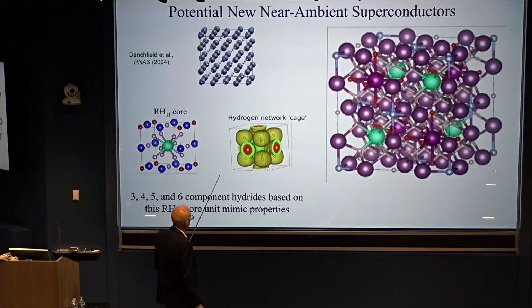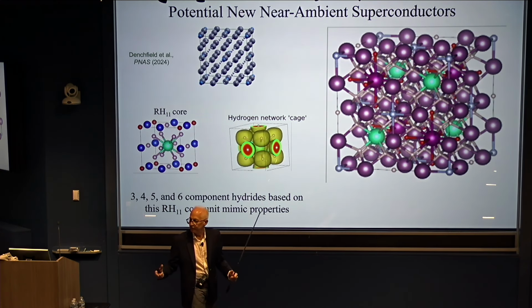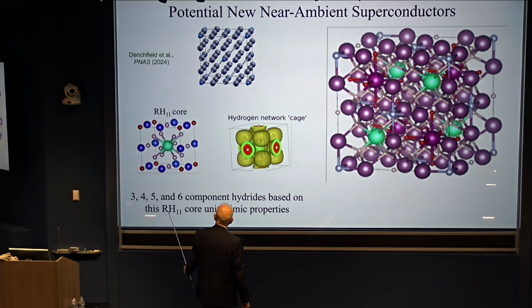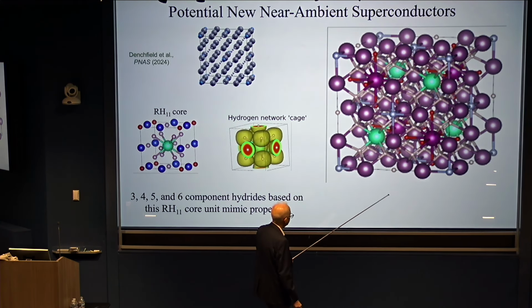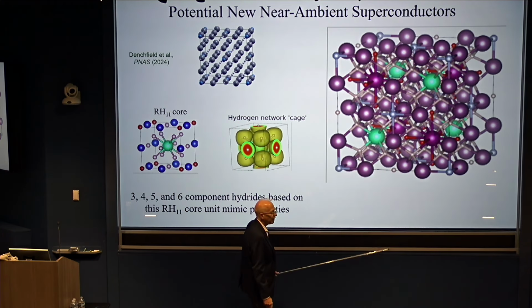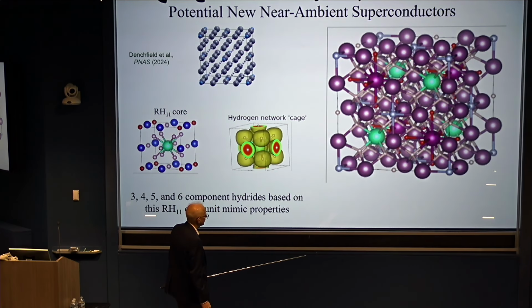just looking at electronegativities and electropositivities of atoms, and he came up with a scheme where the core unit that looks like it's responsible for the intriguing properties is this RH11 unit, and so if you substitute elements in different ways, you can see the preservation of not only the stability, but also the electronic properties. And the more atoms or different elements you include, the more versatility you get and the more stability and interesting properties. So we came up with this picture of a 6-component hydride system that potentially could be a room temperature superconductor that's stable at ambient conditions.